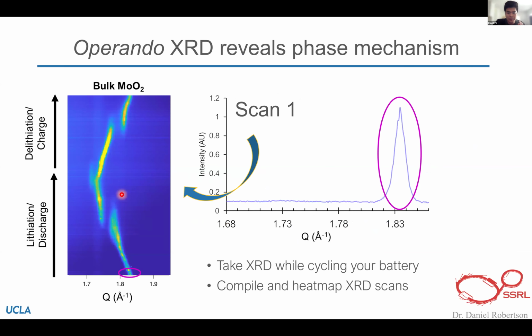And so investigating some of the mechanism of this a little bit more, we can use operando synchrotron diffraction. Using very strong X-rays, we can take our battery materials to a synchrotron such as the Stanford Synchrotron Radiation Lightsource, where we are shooting these very strong X-rays through our battery as we operate it. And what we're looking at here in these heat plots, with just regular MoO2, is a zoomed-in XRD peak. We're looking face down on it.